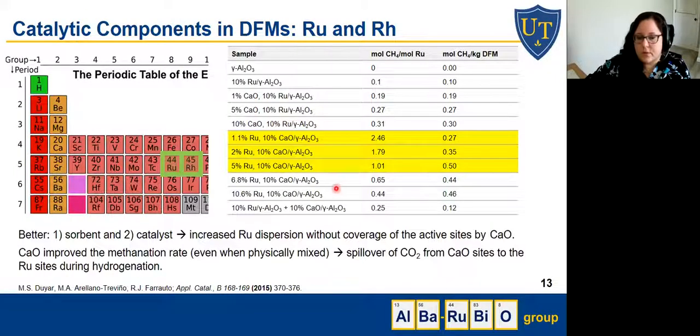Continuing with the ruthenium and rhodium. You might be wondering, if we need a sorbent and a catalytic component, is it better to add first the sorbent and then the catalyst, or the opposite? In this study, they found that it's better to put the sorbent first, impregnate the support first with the sorbent and then the catalyst, because in that way, ruthenium can be more dispersed on the surface without being encapsulated